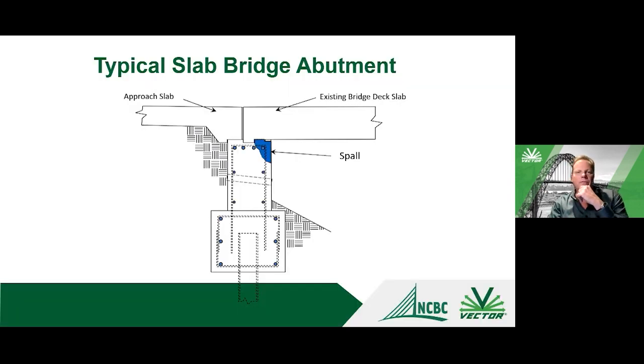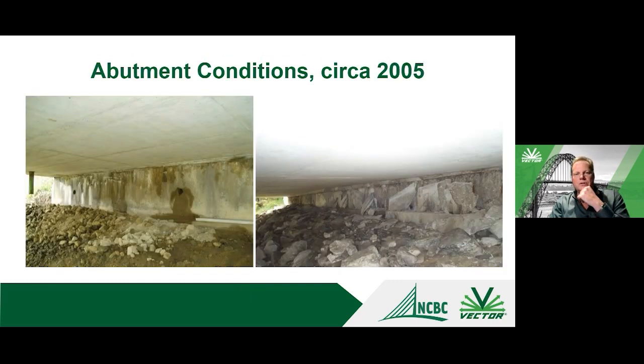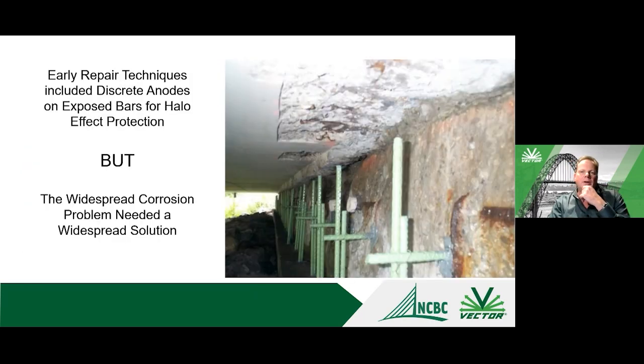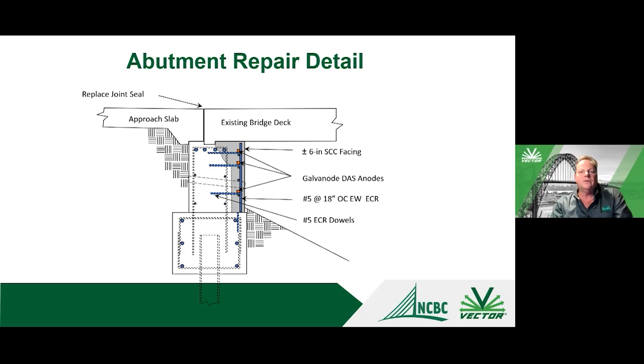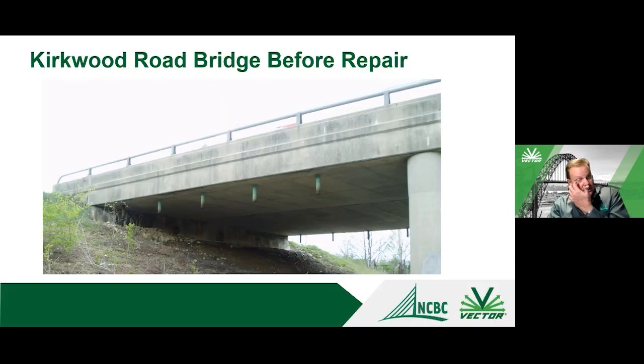Just an example of this: slab bridges. We've been involved in a lot of these in Ohio. In some of the original conditions of the slab bridges, the joint is right over the abutment. In some of the early days, they were doing repairs and started using some galvanic, discrete anodes. But this is more of a severe and widespread corrosion issue. So effectively, they looked at using larger distributed anodes in these repairs, and these are 17, this project's I think 18 years now, and performing very well.